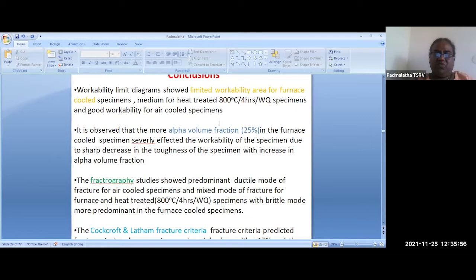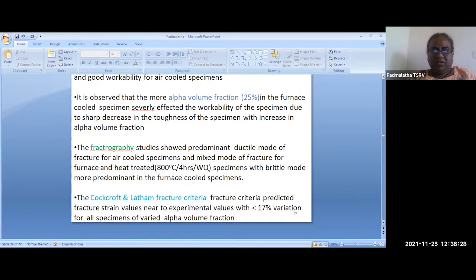Here we have checked the effect of volume fraction of alpha on the workability of the material. And we have seen that as the alpha volume fraction increases, the workability is decreasing, because alpha is nothing but our HCP phase, that is hexagonal close packed phase, which is a very hard and brittle phase. So as this phase increases in the material, the workability decreases because the ductility will be poor. So it's a very simple test. We can work it out in our labs.